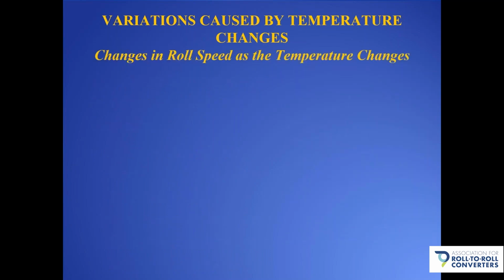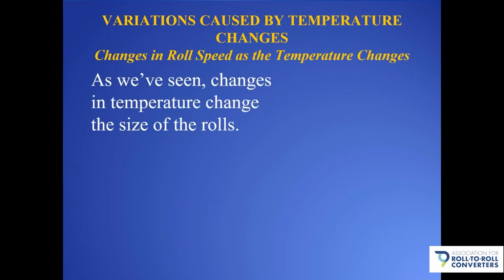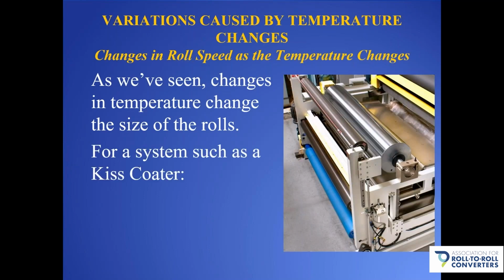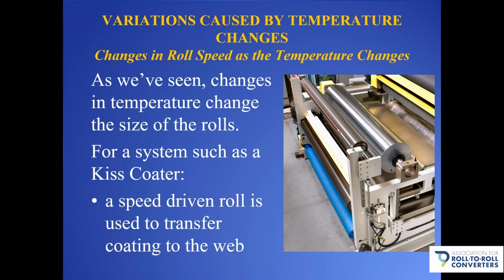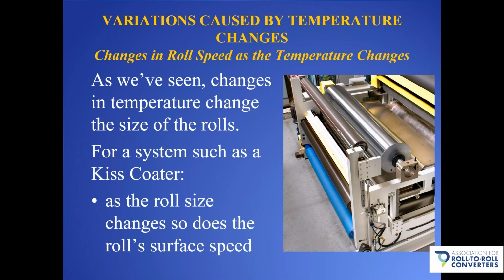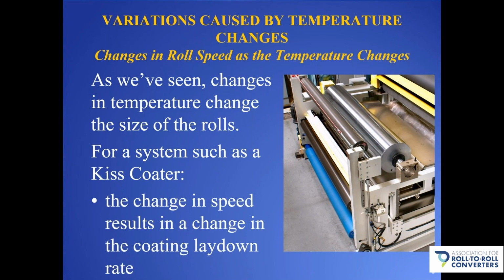Another temperature-related issue is changes in the roll speed as the temperature changes. As we've seen from the previous example, changes in temperature change the size of the rolls. For a system such as a KISS coater like shown, a speed-driven roll is used to transfer the coating to the web. As the roll size changes, so does the roll surface speed, and this change in speed results in a change in the coating laydown rate.